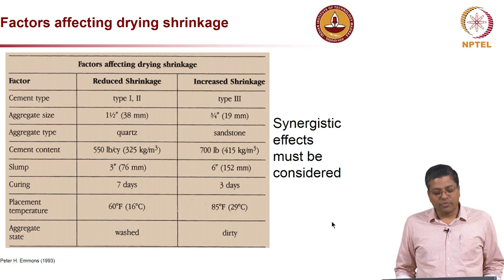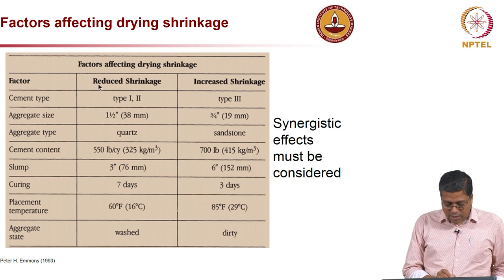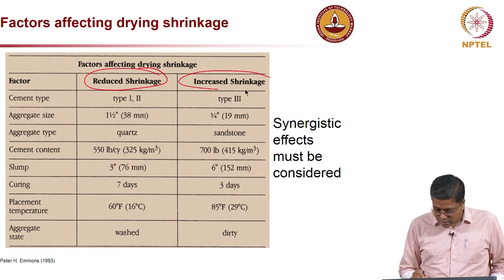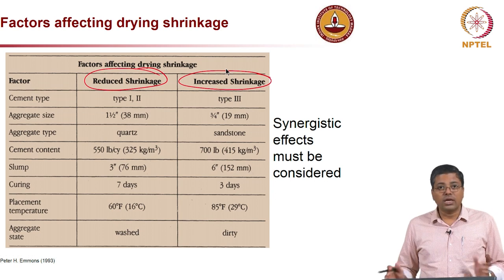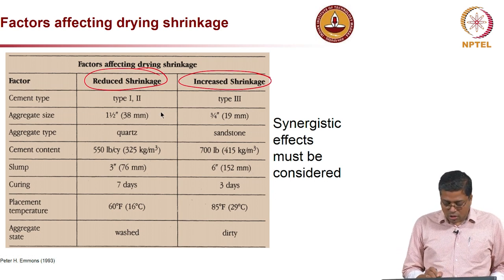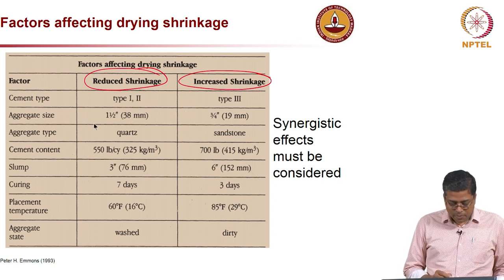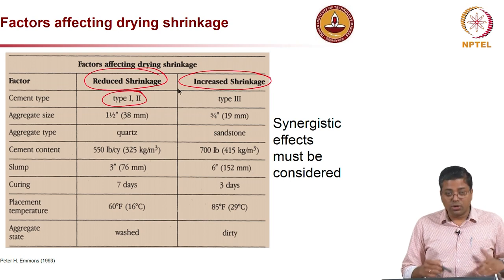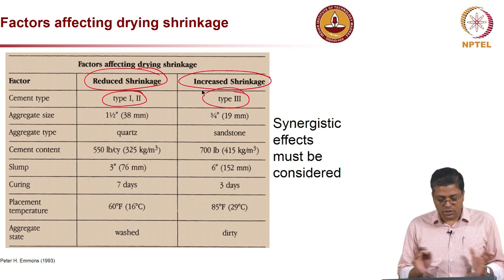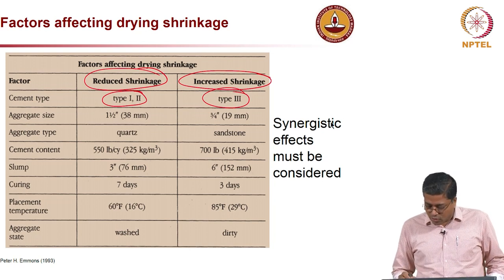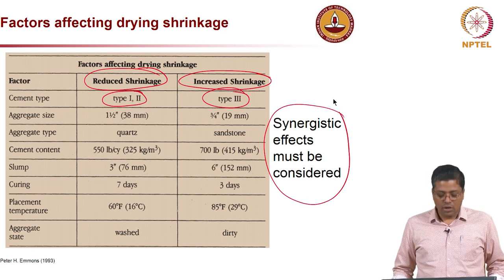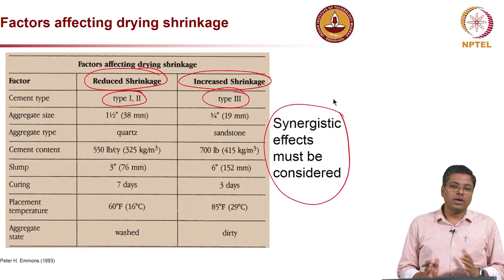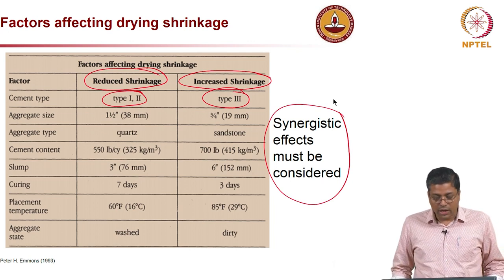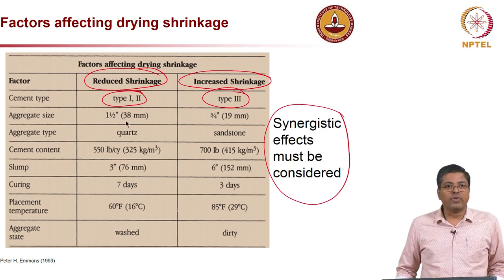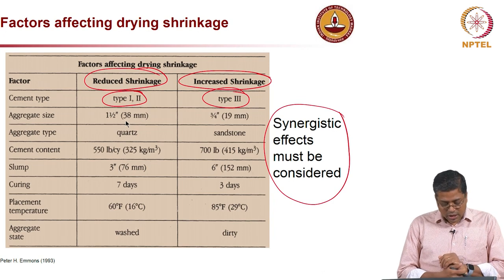Now, some of the factors which affect drying shrinkage. See, this is just an example: in the second column are the cases where shrinkage is reduced, and the third column shows where more shrinkage was observed. But I would like to mention one thing: do not look at only one parameter. For example, if I say type 1 or 2 cement is going to have less shrinkage and type 3 will have high shrinkage, it is not like that. The entire mix design must be considered, and you have to look at the synergistic effects of various parameters while deciding which system will have high or low shrinkage. But this table just gives you a rough idea of some factors, such as cement type.